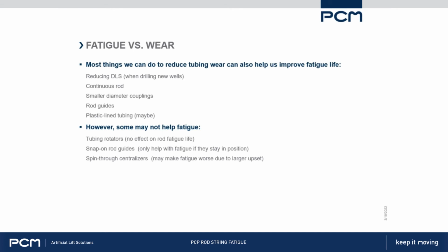Spin-through centralizers. So I'm talking about the ones that go with the coupling. PCM sells these, other companies sell these. They're very, very effective at reducing wear. And they're also really good to use to prevent vibrations from the pump or the drive head from being transmitted through the rod string. So putting a couple near the pump, never right at the pump head, always at least 10 feet above the pump, but put one or two down near the pump and one or two up near surface can actually be very good.